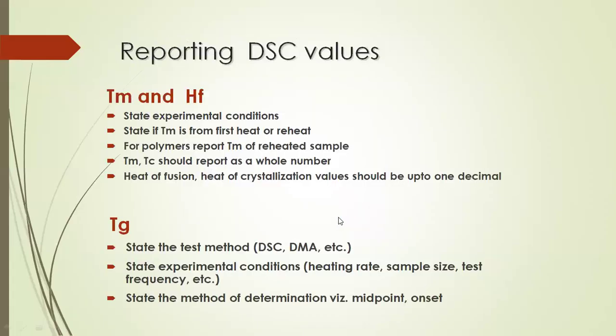Now, very important. I have seen in many recent students that they report their melting temperatures with 2 decimals. No, your accuracy of DSC calibration is not that much. If you see the melting points of indium or tin, we always report it as 156.6. So you also report melting and Tc as a whole number. Don't report it as a decimal point. Always state the experimental conditions, because we have seen that the heating rate and mass affect the TGA curve and affect the melting temperature. So while reporting melting, always state the experimental condition, state whether from first heat or reheat.